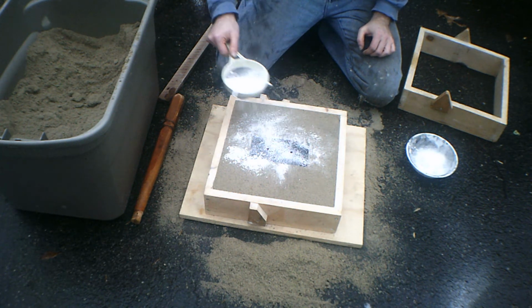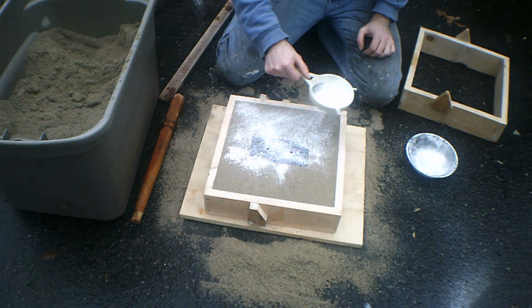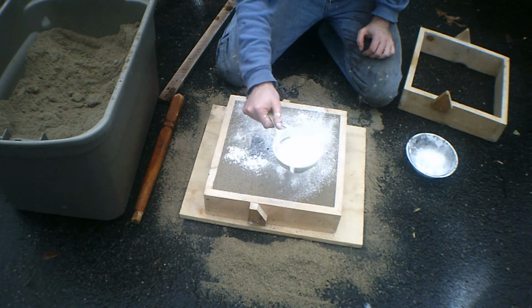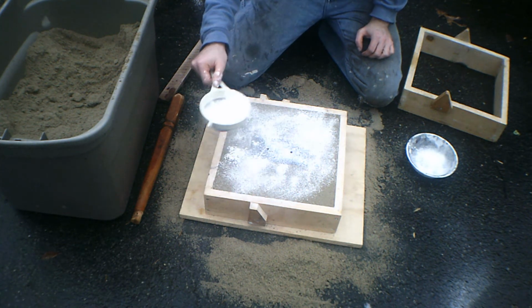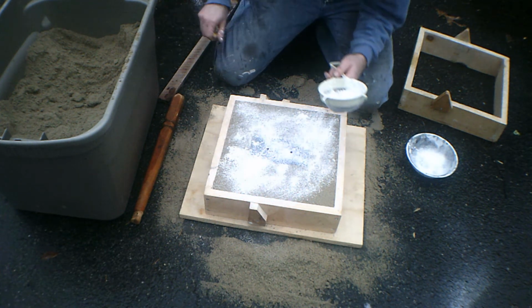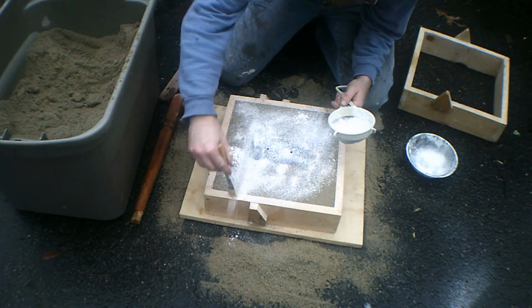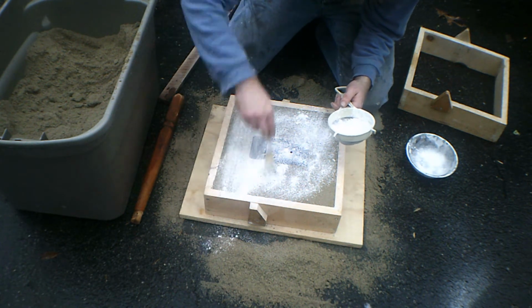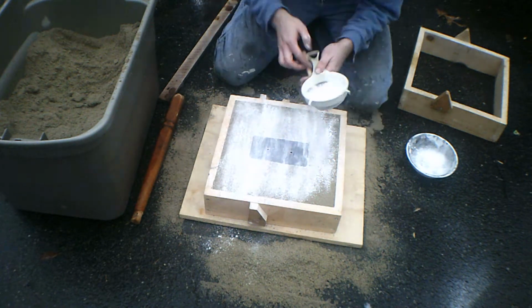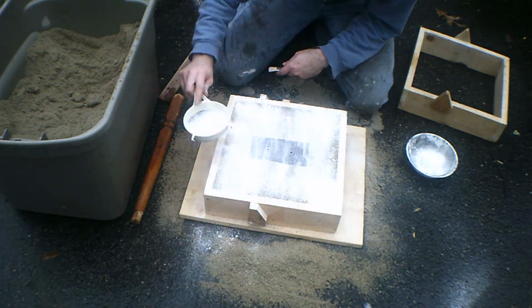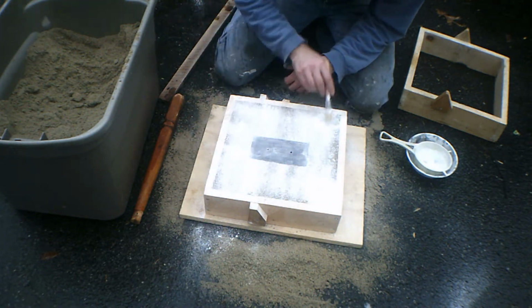A liberal dusting of parting compound needs to go between the two halves, because otherwise when you ram up the top half, the cope, it will stick to the sand in the drag. By using parting compound, it will separate cleanly. A thin dusting is all you need, again, but it needs to be evenly spread, so using a small brush to get it evenly around everything is key here.